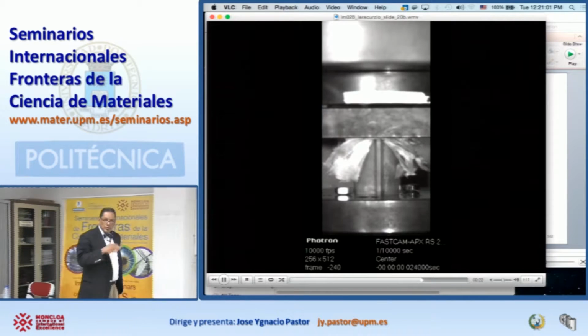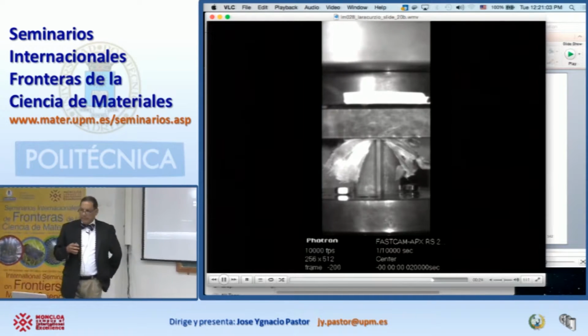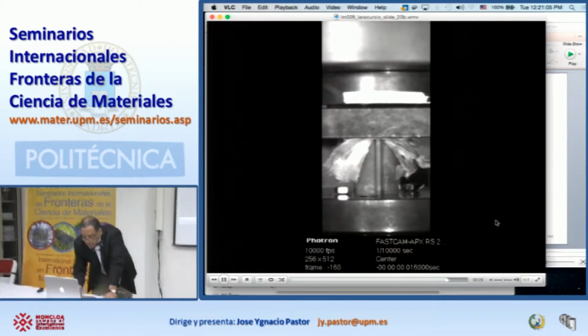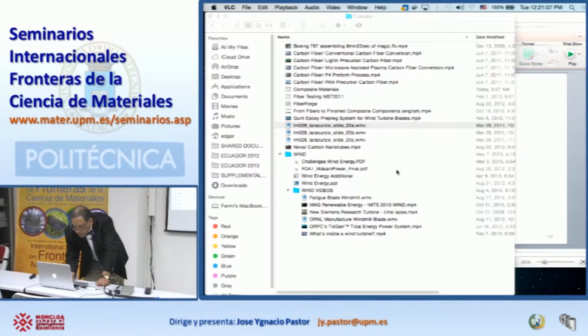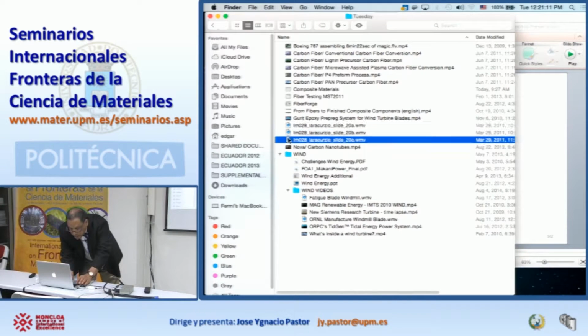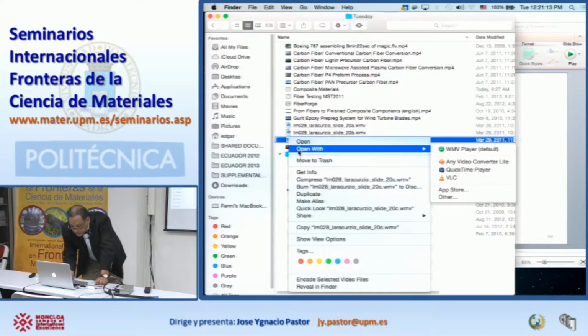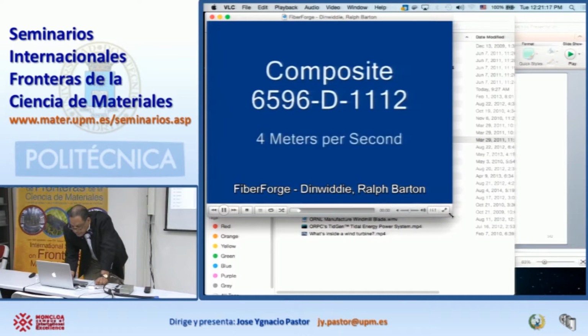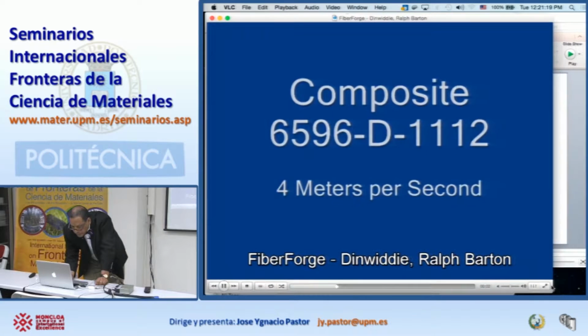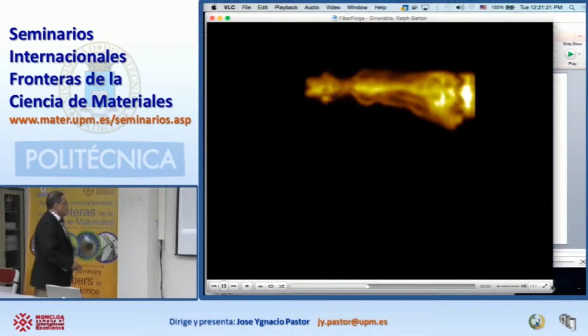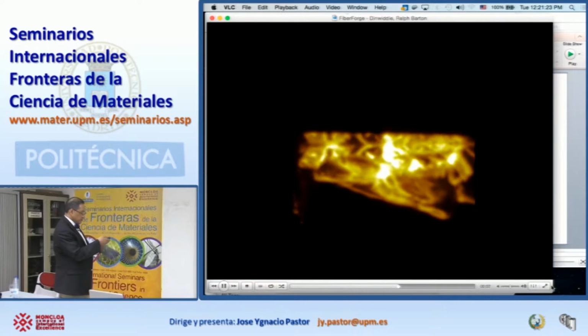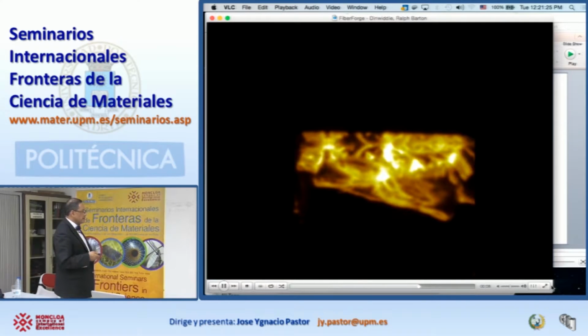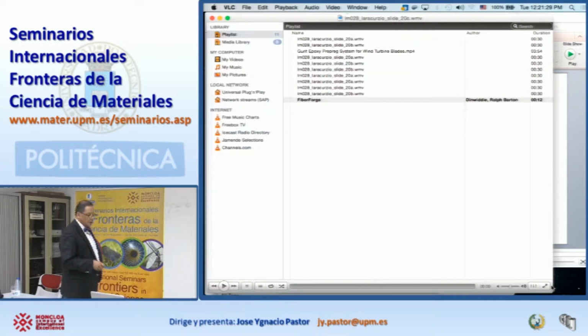And while we were doing these tests, we had an infrared camera, okay? And the infrared camera can be used to measure temperature. So let me show you what we got out of that sample. So now we're measuring temperature. It's a little bit faster. Bright areas correspond to hot zones.